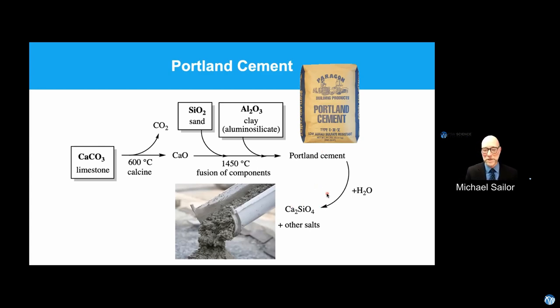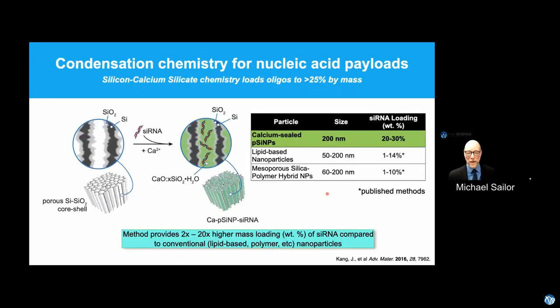So the glue that holds Portland cement together is the same kind of precipitate as the calcium phosphate I showed on the last slide, but you're replacing the phosphate with silicate. What's been used to pack DNA and RNA into small places is basically ion pairing with the calcium. Similarly, you can pack structures together with silicate, and that's how we make the sidewalks that we walk on. So why am I telling you that? We were actually thinking about this when we were thinking about how to get our nucleic acid to pack into our nanoparticles in a really highly efficient fashion. So, a little bit of chemistry there.